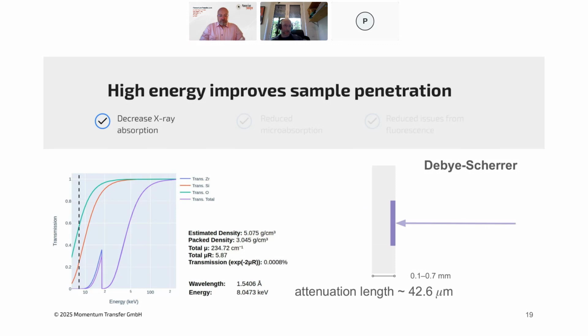If we go to a Debye-Scherrer geometry, which is typically a capillary transmission geometry, you have a similar effect. So same material, same energy, attenuation length is the same. Working with capillaries, you typically use an inner diameter of about 0.1 to 0.7 millimeters with either a glass, borosilicate, or quartz capillary. You can't typically go much smaller than that because then they get almost impossible to load the powders into the capillary. And if you go much bigger than that, I mean, you can already see here that I'm essentially blocking all of my X-rays with this particular sample. So typically you have to use then a filler material, which decreases the overall mass attenuation of the sample. But that means you have, again, far less sample in the beam.